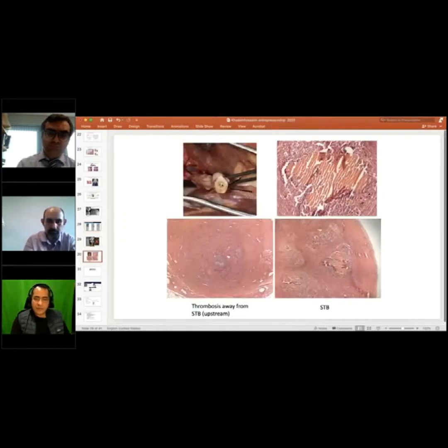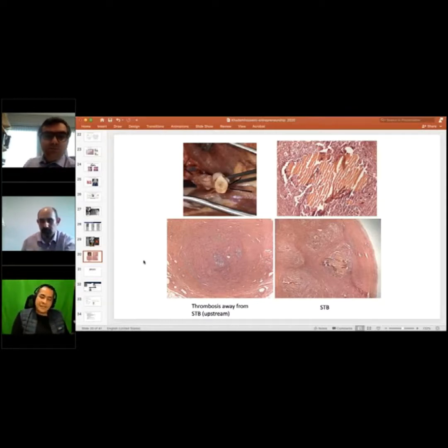So if you put it inside, the blood vessels remain blocked over long periods of time, and basically the material degrades and it's filled with infiltrating tissue. So it makes a fibrotic tissue response, which is the kind of response that we want long term. And many other experiments have shown its efficacy as well as its safety in different types of large animal models.